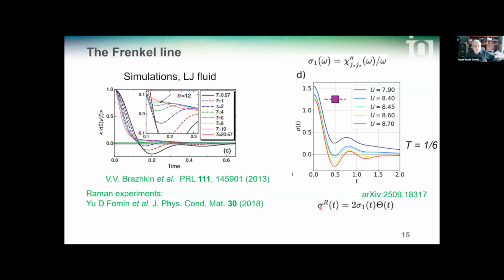So it turns out that the retarded conductivity is just a theta function times twice the Fourier transform of this object. And since the relation between applied electric field and current is through this retarded quantity, a negative value means that the current related to this applied electric field flows, during a certain time t, in a direction opposite to the applied electric field. So this means that there is backscattering.